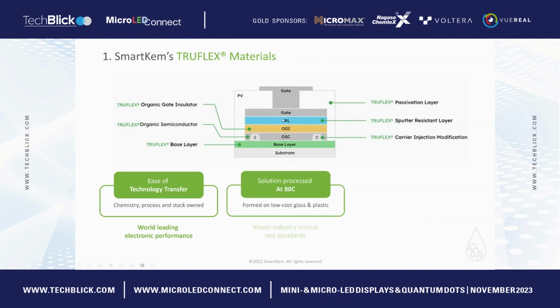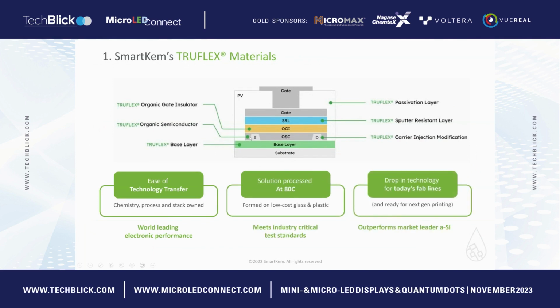This shows the structure of an organic transistor, which looks quite similar to a lot of other transistors. It has 3 electrodes, source, drain, and gate, which are typically metals. And then there is a substrate, which can be either plastic or glass. And then the rest of the layers we develop as liquid coatable inks, which are either UV curable or just coatable and processed with hot plate baking to evaporate off the solvent. So we make a range of different materials, and they're all tailored to work together to provide a highly uniform, high performance transistor with very good stability.